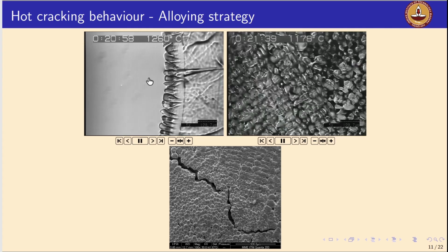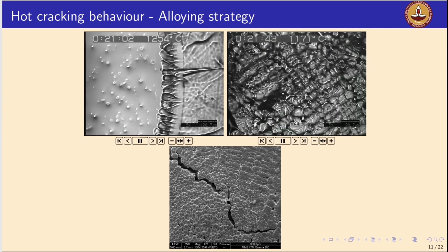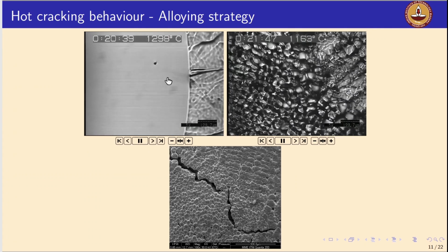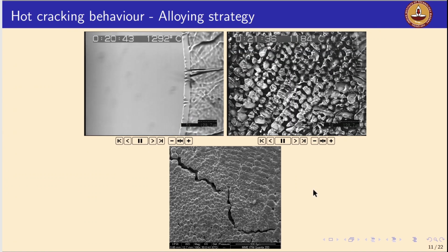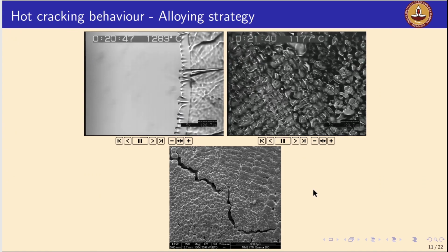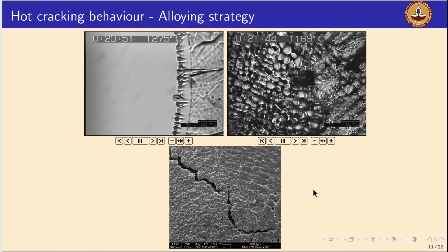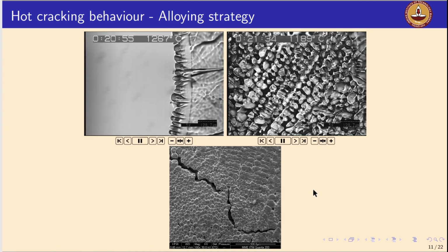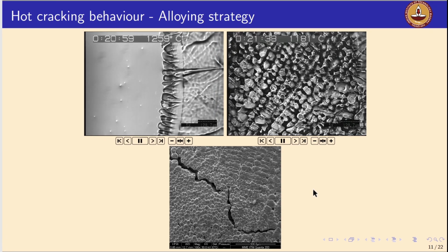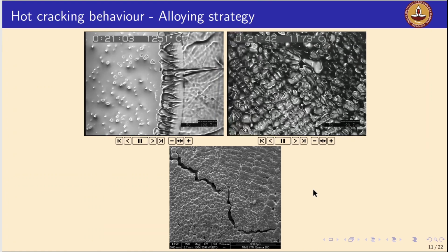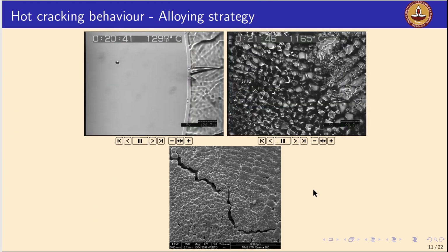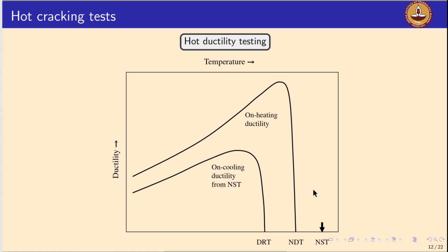Right, and subsequently, when we do in situ studies, we can also see the crack formation live by these high temperature microscopy. Right, as I said, this is a very expensive affair, so we need to have proper equipment, right? And it is also very challenging to visualize the microstructure during solidification at the very high temperatures of this weld. So the best is to have the susceptibility measured using Gleeble, isn't it? So to understand the hot cracking susceptibility for the candidate chemistries, we carry out hot ductility tests. Right, so this is one of the best methods to understand hot cracking susceptibility.